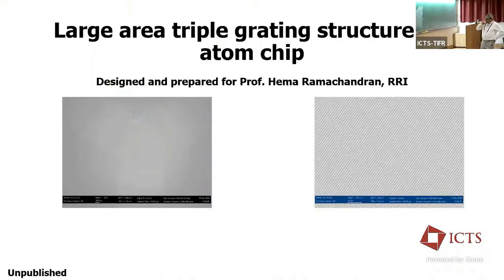So this was my first work, which I started with Hema when she was at RRI. These were 3 gratings at 60-degree orientation. The idea here is that we launch light onto this, and then there are 3 beams which come up, and the diffracted beams will come up about 5 mm from the surface of the sample, so that we can use it for trapping. However, later, after Hema's demise, these samples were given to RRI, and they measured it and gave feedback that this central region is also giving a spurious beam.